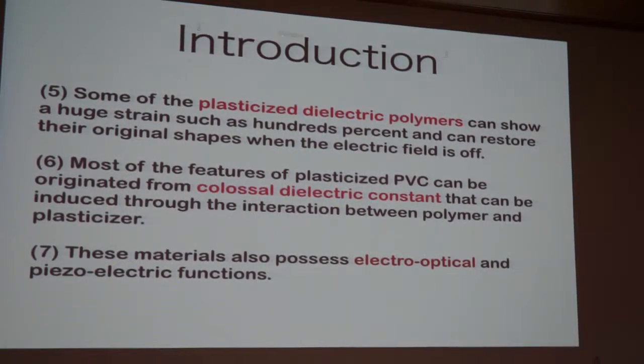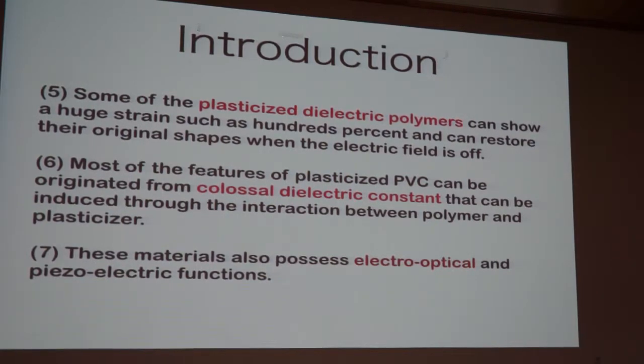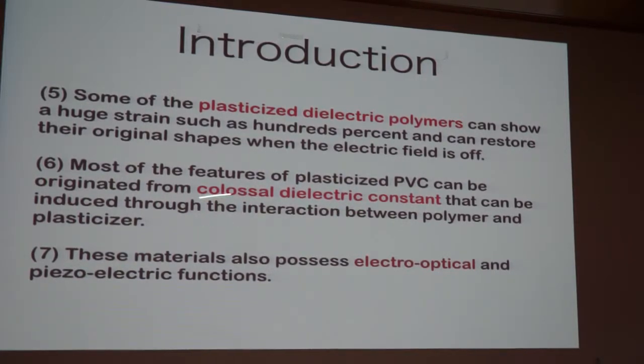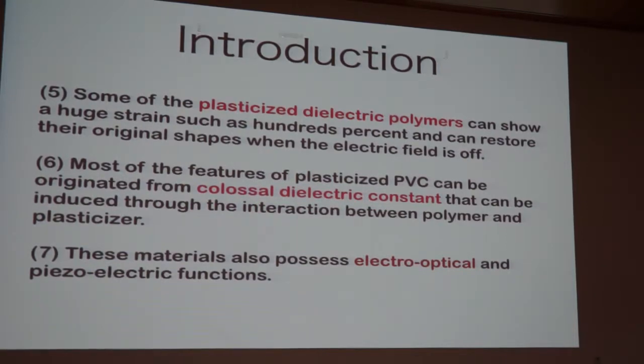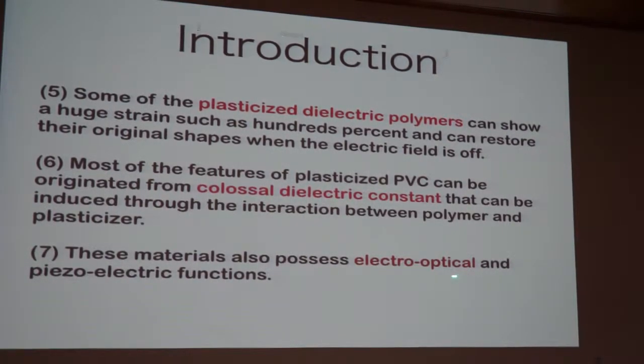Most of the features are of plasticized PVC, polyvinyl chloride. Most of you know polyvinyl chloride has been used conventionally and widely, and has been believed to be inactive to the electric field. But it is electrically active. And the reason turned out recently; actually we found the phenomenon 10 years ago, but I couldn't believe it. So I tried many experiments using many students. And the colossal dielectric constant was found in the low frequency range. That is very important for PVC. That's the origin of the huge strain generation by the DC electric field. These materials can also possess electro-optical functions or piezoelectric functions too. And I'd like to introduce this kind of phenomenon later.